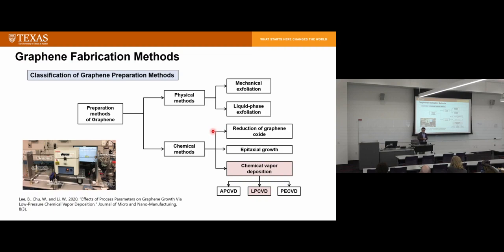There are chemical methods: reduction of graphene oxide, that's one, and epitaxial growth, where you usually grow graphene on top of certain wafers, so you can make this basically for microelectronics applications. Very high quality graphene, but it's not very large scale. Chemical vapor deposition: you have APCVD, low pressure CVD, and plasma enhanced CVD. Those are the methods that have potential to grow large scale graphene.